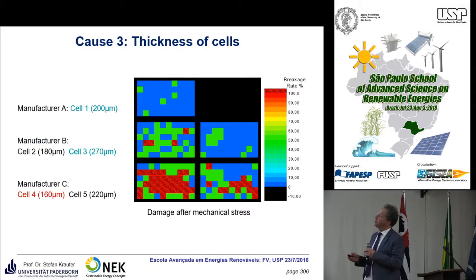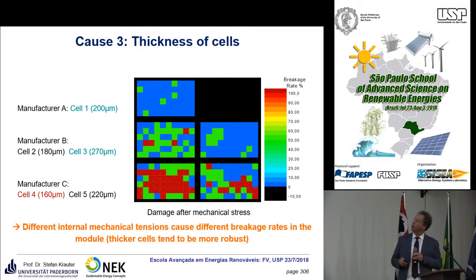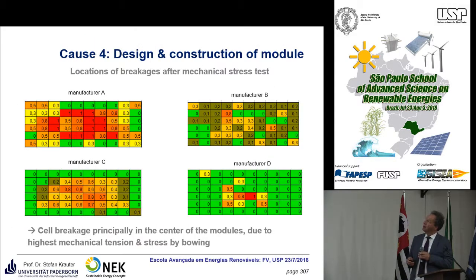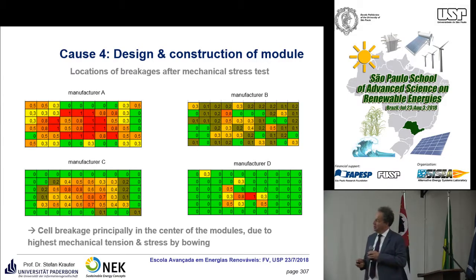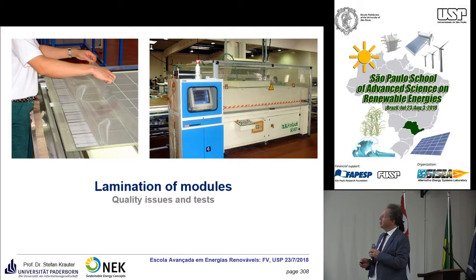You can influence that if you use thicker solar cells. Here, you have, for example, a thinner solar cell, and this is more sensitive to cracks, while the thick solar cell here is less sensitive to cracks. Here you can also design a little bit: make thicker glass and thicker frames and so on. So you can also reduce the stress factor.